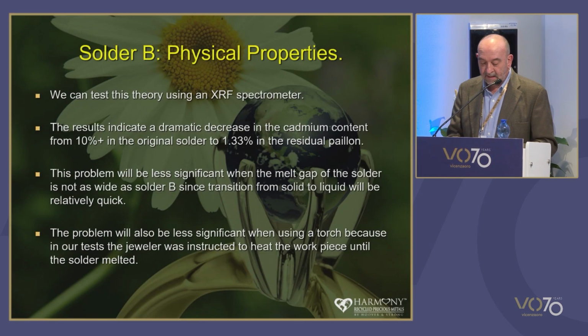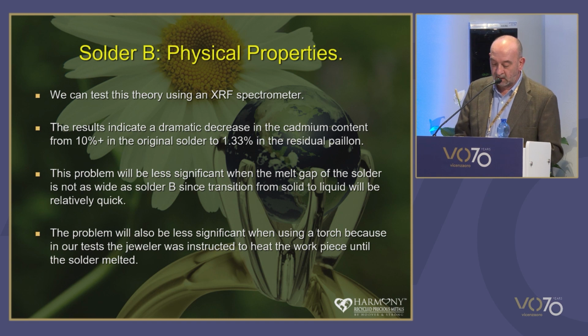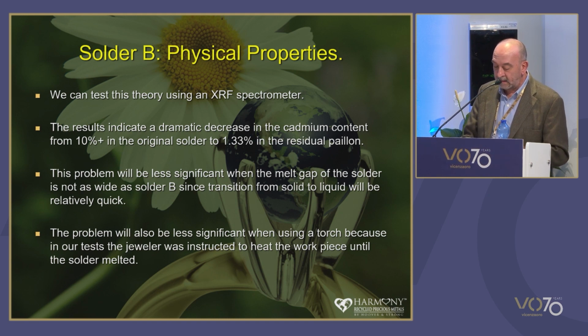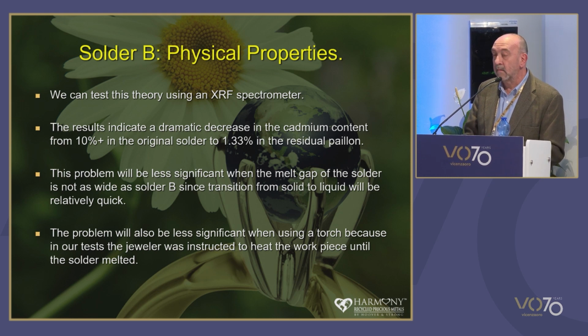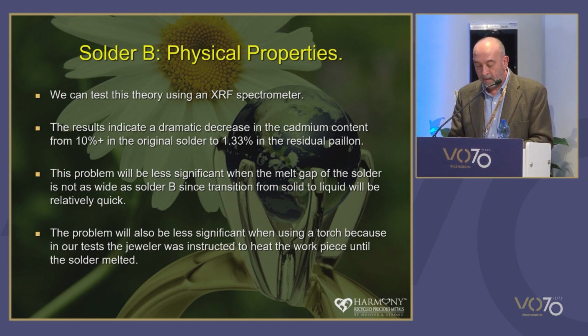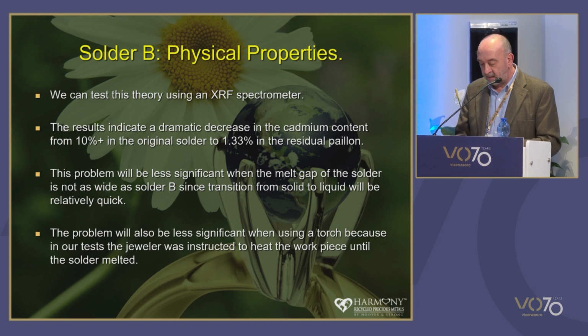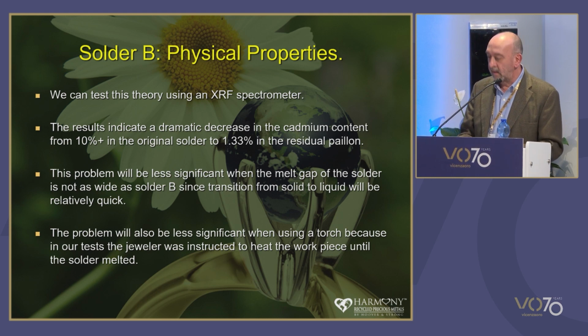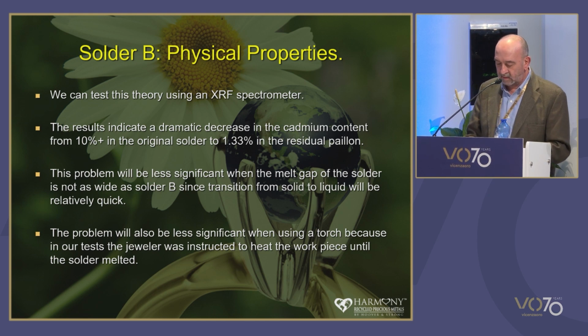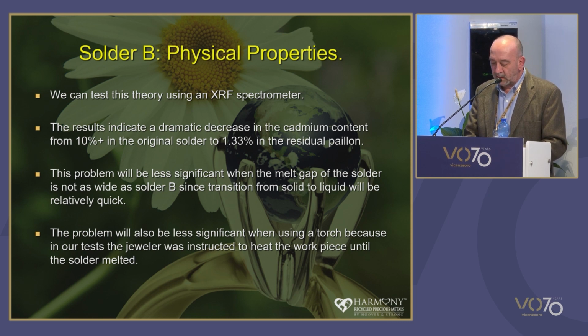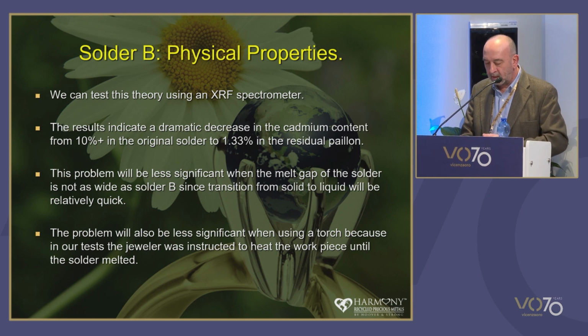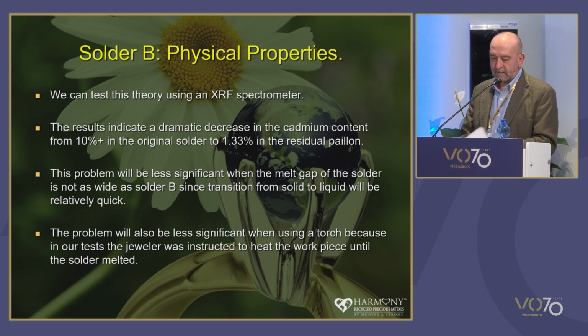So we gave this a quick test and we did some analysis on the residual piece of solder that was left in one of the solder B tests. And typically the solder's made up with 10% cadmium. But when we tested the residual piece, it only had 1.33% cadmium in there. So we believe this loss would raise the melting range of the solder above the furnace temperature. It's going to be less significant when using a solder with a narrower melt gap because you're going to achieve liquation very much quicker.